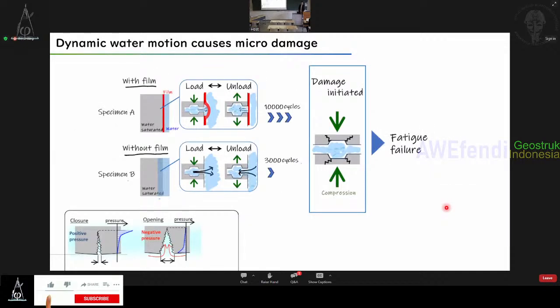So perhaps also it's because when you have exchange of water, you will have a gradient of swelling and a gradient of drying shrinkage that can lead to initial stress inside the specimen and even cracking. Initial swelling or deformation is almost the same between A and B. And what do you mean? What I mean is because you have a gradient of water content inside the specimen. In this case, there's no gradient, because water can go in, can go out.